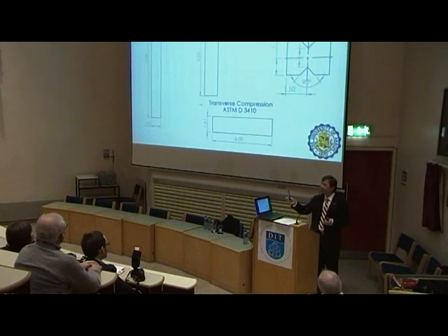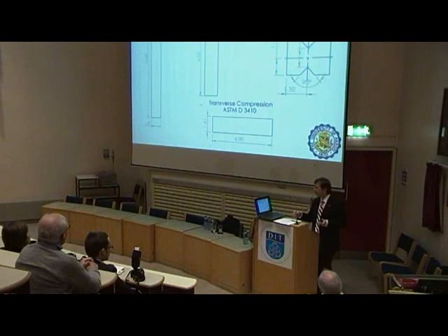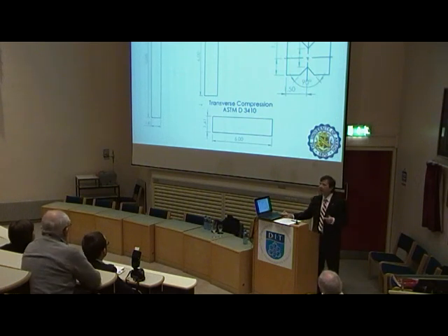Unfortunately, this is a coupon for the simple tensile test, and you can see that the outside edges basically cut through the bundles that are plus minus 60. And this has, we found, a consequence on the results of the test. So we had to develop a new test outside of the ASTM standard, and we were looking first of all to understand the so-called edge effect, and you can see this edge effect in the DIC methodology.